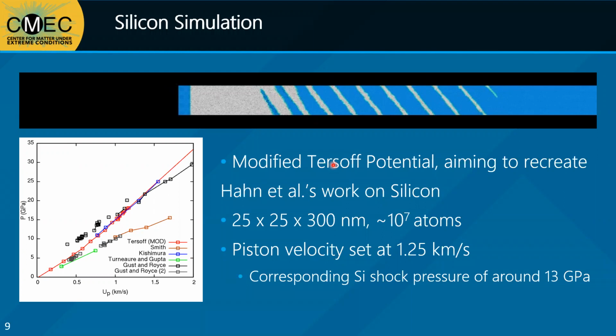Yeah, so a lot of this research was based on Shiteng Zhao's work, which was studying those amorphous bands in silicon, although they were actually BCT5 bands with small amorphous pockets. And in his work, he described the direction of these bands as trying to adhere to the cone of maximum shear, which is along the loading direction and about 45 degrees away. However, the closest slip system to that direction of maximum shear was about 54.5 degrees, and that slip system is where these bands are forming along. Okay, so you do see them in the simulation at 55. Yes, 54, sorry. Okay, that's cool. Thank you.